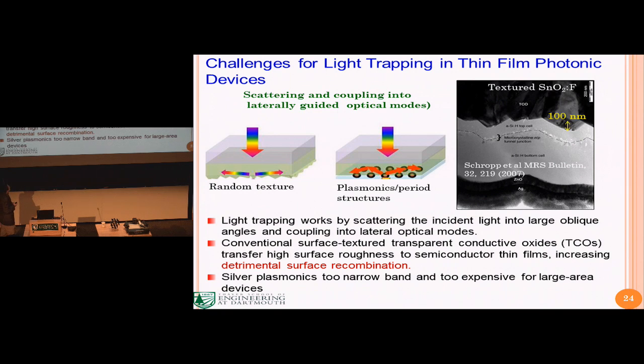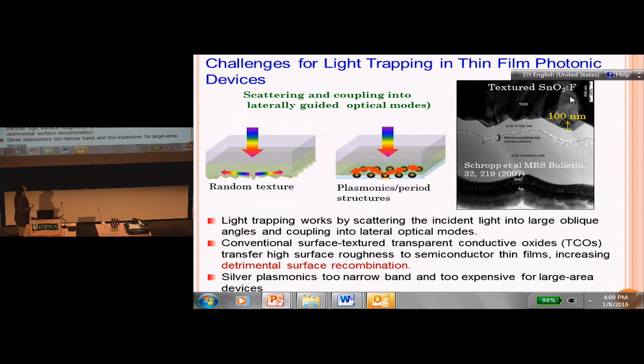So we were thinking maybe we can do something that combines the merits of the two approaches, which is, instead of using the surface texture in the TCO, we can engineer some scatterers into the TCO. Because tin oxide is very commonly used, originally we were thinking that we can make it slightly tin-rich so that we can add additional tin scatterers inside the material. So that's our original thought.